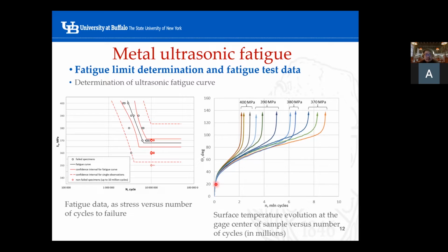We can say the first rapid increase part is phase 1, due to internal frictions, and it increases very fast because it can be achieved in only several seconds. In those seconds, there's not enough time to actually activate heat dissipation, so initially we have very high, rapid temperature growth.